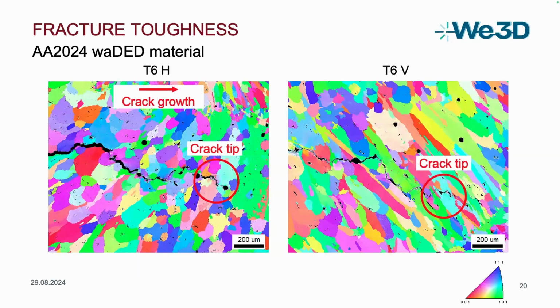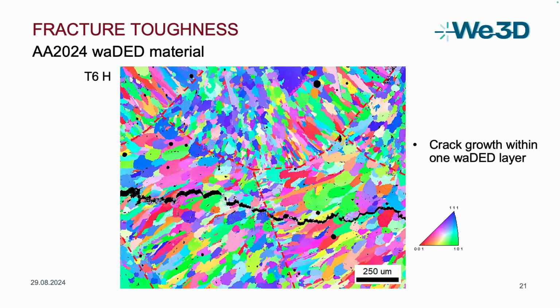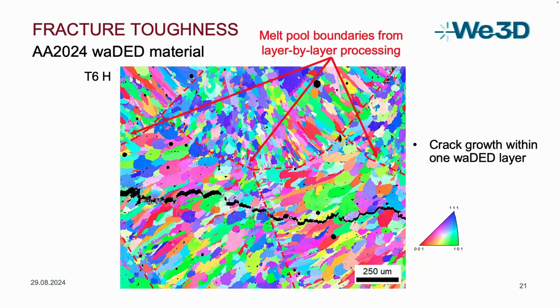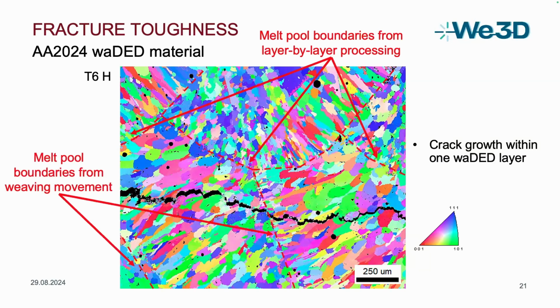And in the EBSD, again, we can see our wire arc DED microstructure with equiaxed and elongated grains. The crack basically goes along the grain boundaries. It doesn't really matter if we have equiaxed grains or elongated grains, but the crack propagation is controlled by defects such as pores and micro shrinkages on the grain boundaries for both orientations. And here in this area, we can see that the crack is within one DED layer, so it is not along the melt-pool boundaries. Here in this upper region, we can see the melt-pool boundaries from the layer-by-layer processing. And furthermore, with the tilted lines, we can also see the melt-pool boundaries from the weaving movements.